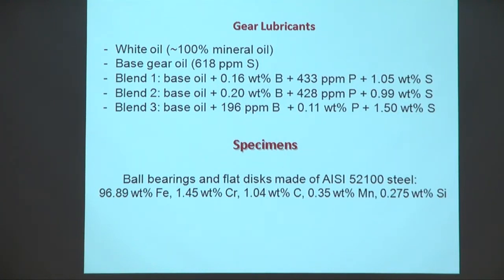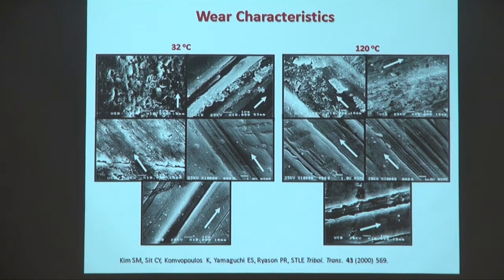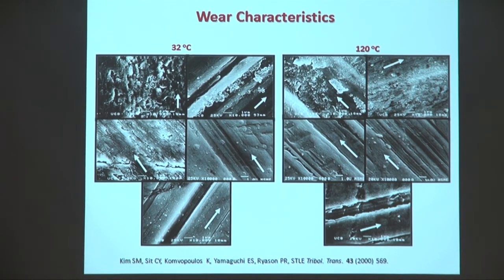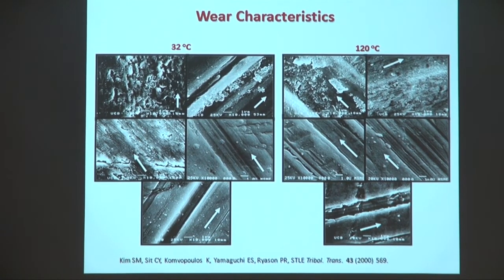So throughout what I present here, we will be looking at bearing steels, standard bearing steels. We are not going to bother with tweaking the chemistry of the steels, which are typical 52100 balls sliding against a disc in the presence of these different oils. So let's take first a look and see what typical features we can see at low temperatures and high temperatures. You can think of this as the engine being relatively cold when you start the car, and this could be a hot, maybe more than the typical high temperature, so it's sort of an upper bound, worst case scenario of the temperature of the engine after steady state.